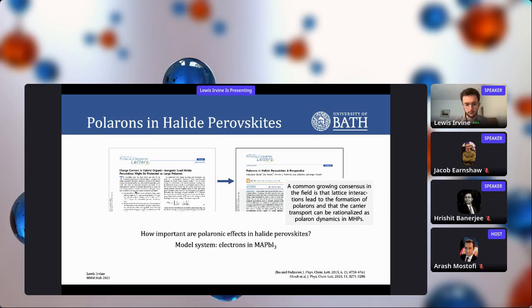So this traces itself back to a letter back in 2015 by Zhu and Podzorov, where they hypothesized that charge carriers might be protected from scattering events by their incorporation into large polarons, which I'll explain in the next slide. And they use this theory to explain some of the slightly strange transport properties of halide perovskites, including a bit of a strange mobility temperature dependence, which I'll get to at the end of this presentation, but also things like their exciton dissociation energies and a few other things as well.